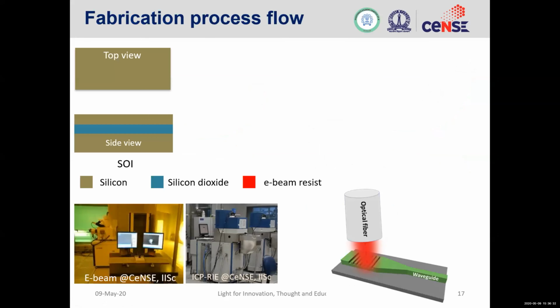Here is an example which I'm about to show. On the bottom right, I'll try to explain how to achieve this kind of structure, where you would like to pattern a tapered structure, a waveguide and a corrugating structure, which is also known as a grating. The process is similar. You start off with an SOI wafer, where the brown color indicates silicon and blue is silicon dioxide. The first step is to coat and do electron beam lithography. This is after you pattern and then develop. The exposed part gets removed in the developer.